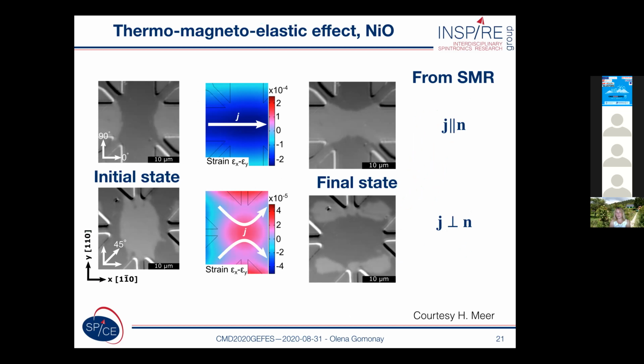We return back to nickel oxide, which has, as we assume, opposite magnetoelastic constant compared to cobalt oxide. So in cobalt oxide, we see switching of the Néel vector to a perpendicular orientation to the current. What we can see in the nickel oxide is that initially we have seen switching parallel to the current, but then we decided to try different geometries of the current and see whether we can manipulate the direction of switching.